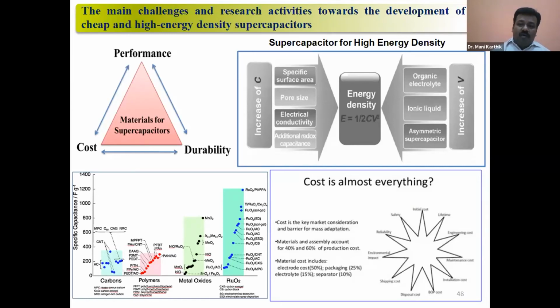But what is the problem? The major advantage of carbon is long durability, because it's an EDLC mechanism, as I said, adsorption and desorption. There are no chemical reactions and no electron transport. So in this case, the carbon life cycle is generally 1 million, 10 lakh cycles of charge and discharge, and the lifetime is generally 10 years. Maxwell is reporting this. Maxwell is one of the well-known companies in the world manufacturing supercapacitors. I will explain in other slides. You can see that the Maxwell capacitor using activated carbon has 1 million charge-discharge cycles. That's the reason they are using carbon.